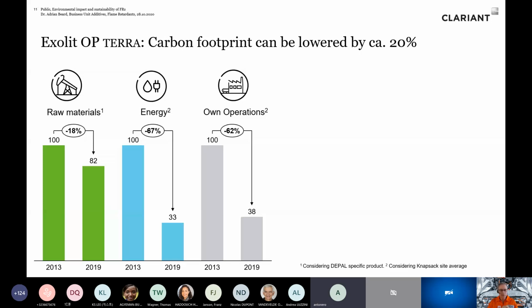What has the flame retardants industry been doing about this and about sustainability impact? Here an example from Clariant. Our brand name for our flame retardants is Exolit, and the Exolit OP Terra types are a type of phosphinate-based flame retardants that we are introducing into the market that are based on renewable carbon sources. And with that, we can show that the carbon footprint can be lowered by about 20% of the flame retardant. And this reduction by 20% is because the raw materials, and that has the main impact, their carbon footprint is reduced by around about 18%.